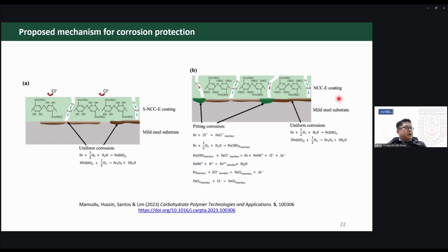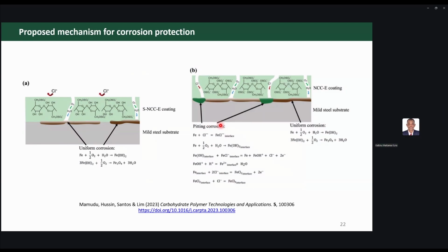But when you just use nanocellulose on its own, we did see that chloride ions can still penetrate the coating, and chloride ions are very dangerous because they can actually cause something called pitting corrosion, which is actually the loss of material that goes deeper.